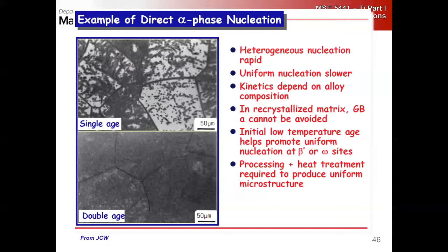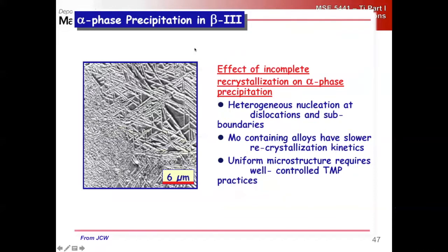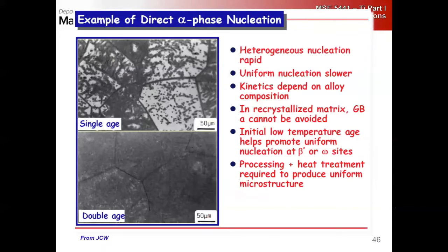These are not super critical. These are some additional slides from Jim Williams. Note the Comic Sans. And so this is just direct nucleation of the alpha phase. Depending on some alloys where you don't get as easy omega phase nucleation, you can still heterogeneously nucleate alpha by a direct quench.